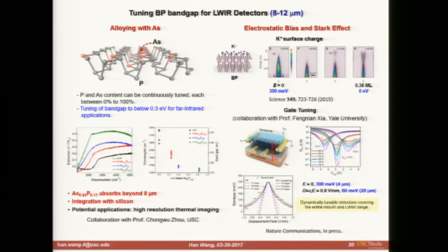Firstly, these dopants are not very stable—heat up the sample a little bit and these dopants will be gone, so that's not attractive for devices. Also, by doing this doping, you lose the dynamic tunability. You can dope the sample and cause the band gap to reduce, but you get a fixed band gap after that.